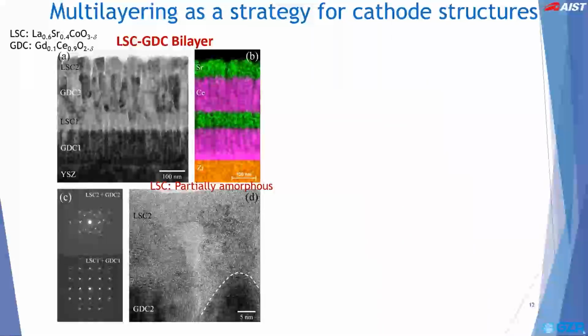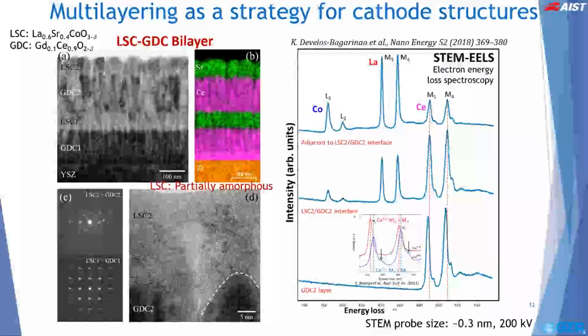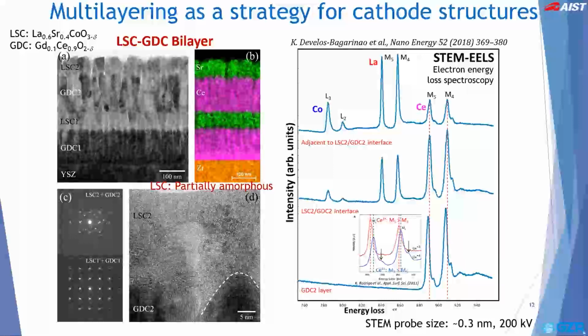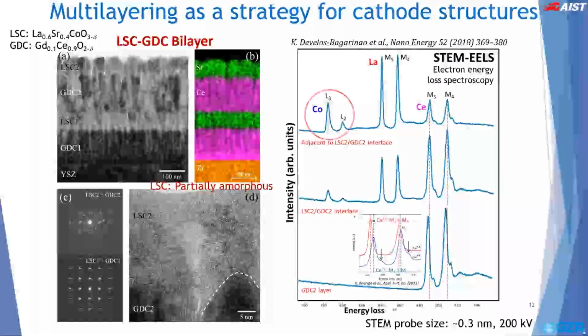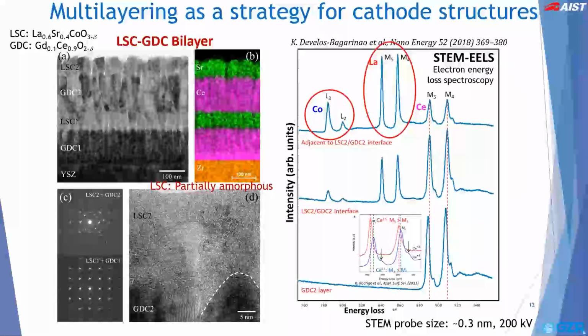Another approach we explored is the multilayered structure prepared by alternately growing two different types of thin films. The figure on the left shows a typical cross-sectional TEM image of a lanthanum strontium cobalt oxide, or LSC, and gadolinium-doped ceria, or GDC, in a multilayer composed of two pairs of each film. Each layer is characterized by nanocolumnar grains and appears uniformly stacked on top of each other with clear, well-defined interfaces. To further probe the electronic structure of the samples, we also performed spatially resolved STEM electron energy loss spectroscopy, or EELS, measurements on the multilayers. On the right is a typical EELS spectra depicting the L3 and L2 edges for cobalt, M5 and M4 edges for lanthanum, and M5 and M4 edges for cerium.